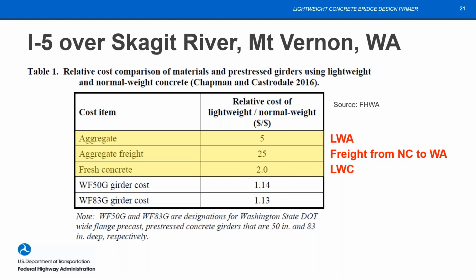Now that's still significant. But then by the time you get down to the girders themselves, the price per foot of girder was less than 15% more than for a normal weight girder. And I think that's very important to remember, that even though the cost of the lightweight aggregate and freight were so much higher than normal weight, the cost of the completed girders was only 15% more.